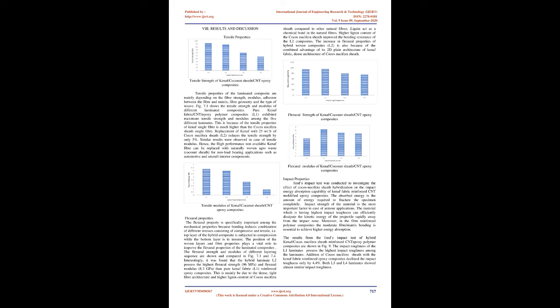7. Tensile testing. Tensile test was conducted as per ASTM D3039 standards. The specimens for tensile testing were cut from the laminated composites using bandsaw with a sample size of 120 mm x 20 mm x 3 mm. Accurate surface finishing could be obtained using emery paper. Tensile strength and modulus were measured by using an Instron 5566 universal testing machine. The magnitude of load and the rate of loading were 10 kN and 5 mm/min. In each group 5 identical test samples were tested and the mean value has been tabulated.